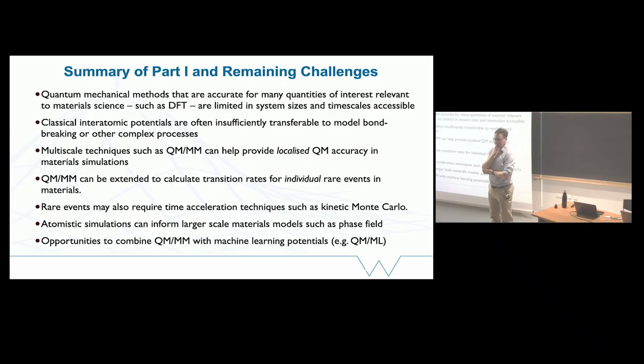You break it when the forces exceed some threshold, I guess. But when the bonds will break, do you know that from experiments or some empirical knowledge, or can you know that directly from the forces? No, it comes directly from the simulation. You don't have to put in any threshold or anything into the simulation. You're applying loading in some prescribed way, and you see in your trajectory the observations, which you can then compare to experiment. So you don't put any experimental information into the calculations that I've shown you at all. That's important to clarify. Okay, so the bonds just break at some point?